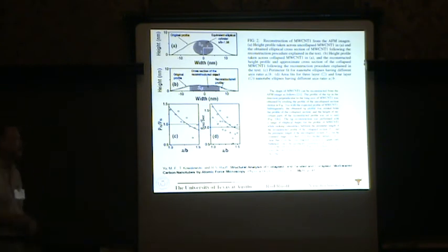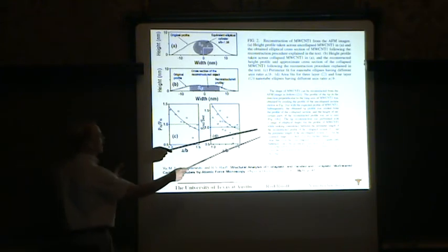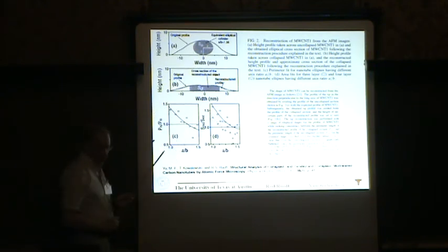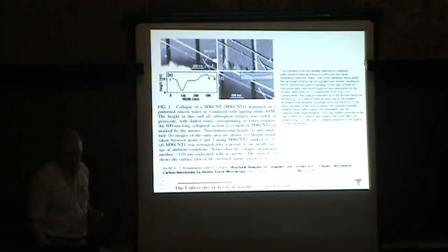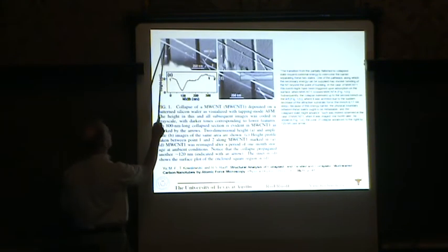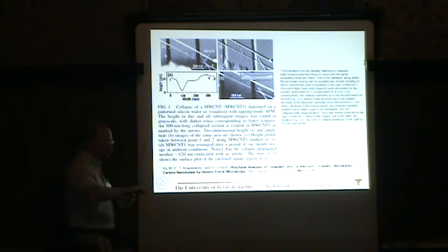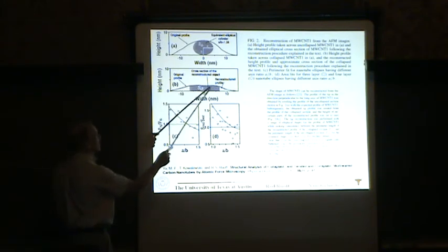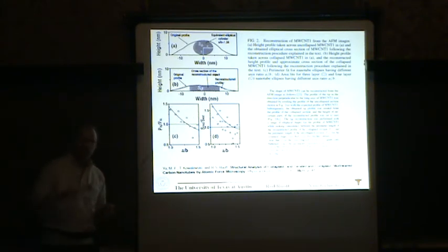Those of you who might be expert, there's a way of backing out the structure of nanostructures through this mathematical algorithm where we could assume an elliptical shape. So even in the region where it wasn't fully collapsed, such as up here, it was deformed into an ellipse, and not a perfect cylinder. And then in the regions where it's collapsed, in a moment I'll show you a profile.